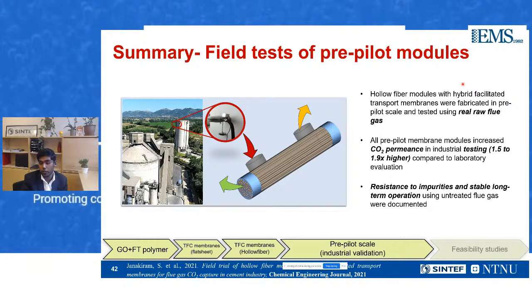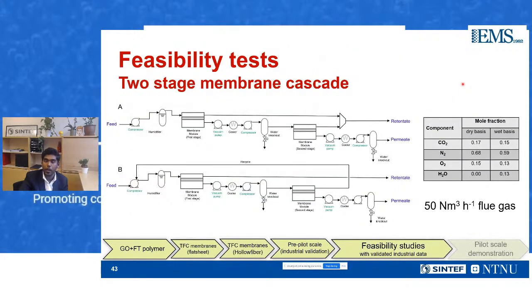And that reason is because of the good conditions at the industrial scale testing. And we also proved that the membranes are good for impurities and also have long-term stable operation. So now that the membranes have been validated, we got the data from the validated membranes, and we wanted to use that as a basis for our simulation study to design a membrane system with 2 stages to reach the targets of CO2 purity and recovery.